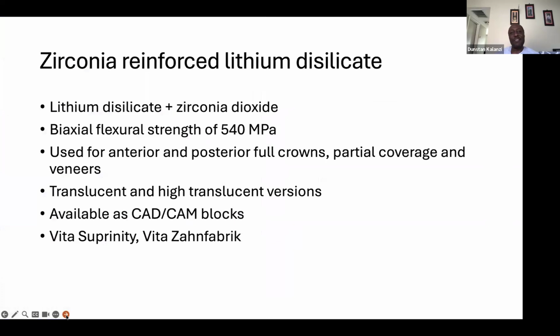Then we have zirconia reinforced lithium disilicates. So you just have the disilicate plus zirconium dioxide, which results in improved flexure strength. And you're talking about 540 megapascals. It has the same applications as the lithium disilicate: for your anterior and posterior full crowns, partial coverage like your onlays, your three-quarter crowns, and the veneers. And you have both the translucent and the high translucent versions. And they're available as CAD-CAM blocks. Because there are different companies selling different products, this, I believe, is from a German company, Vita Suprinity, or the brand is Vita Suprinity.